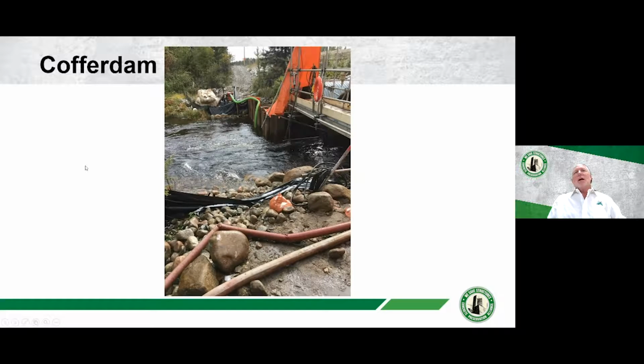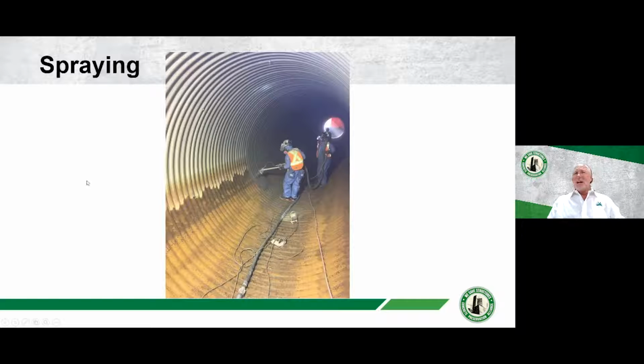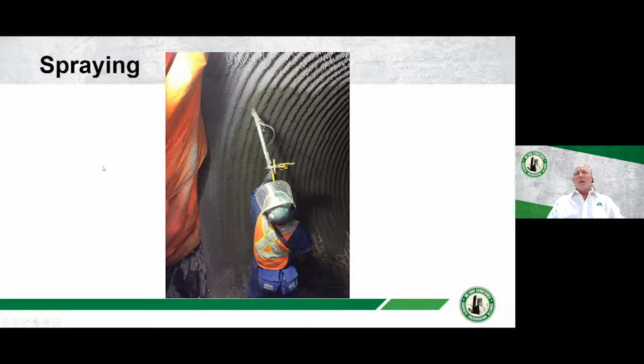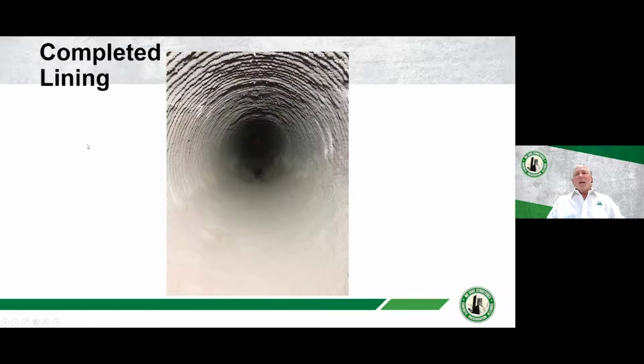In this case, the river was diverted by cofferdamming. So we cofferdammed off one culvert, allowed the water to flow through the second culvert, and we were able to work in a dry environment that way. Because of the size of this culvert and the configuration, it was decided to spray them by hand. So you can see here, putting on the initial pass of the liner, going back and finishing it off, and again getting a fully lined structural pipe inside the pipe of the culvert.